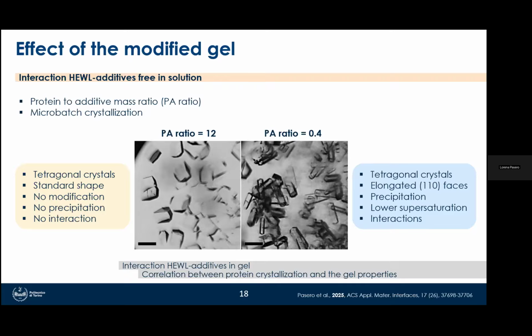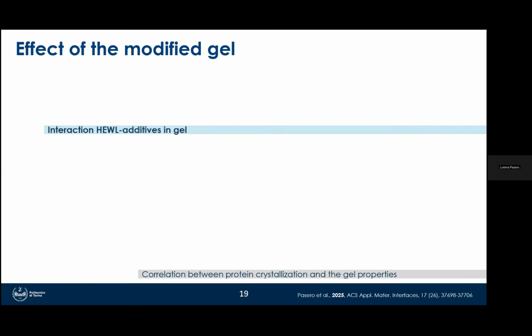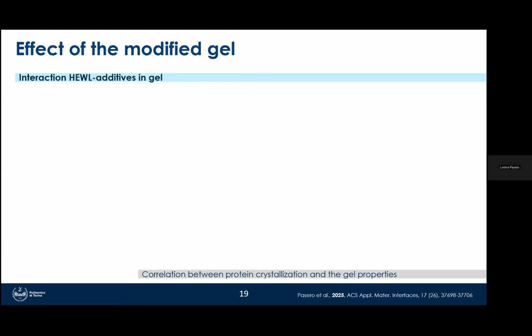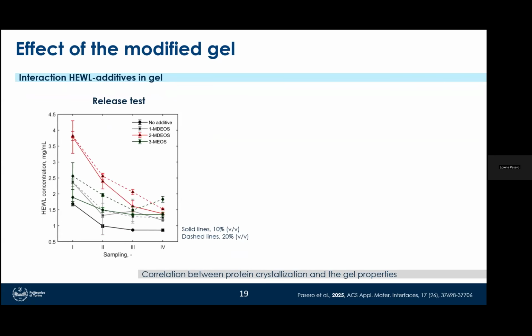So after that, we concluded that in gel-like conditions, the additive's action was mainly related to the modification of the gel, with respect to the interaction of the additive and the protein. And so the next step was assessing the protein-additive interaction in the gel. To this end, we performed release tests of protein from a gel to a buffer solution, which was placed in direct contact with the gel.